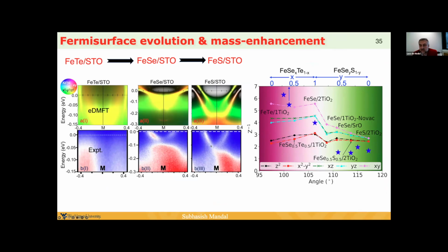Okay, because you were specifying this selectivity in the masses, and it's clear that when you have selectivity, you should have different estimates of the mass enhancement depending on the orbital character. If you have different ways to estimate the mass enhancement based on the experiments, when you are very selective, they start to diverge among each other. I completely agree.